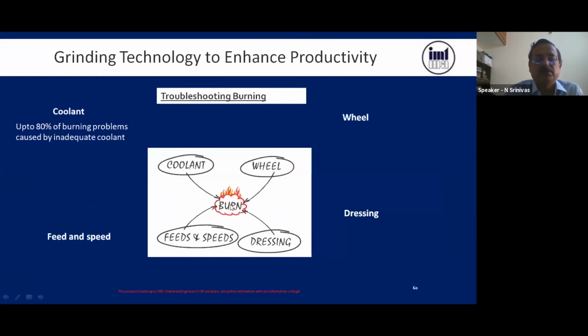For example, burning comes. What are all the causes for burning? With respect to coolant, up to 80% of the burning problem is caused by inadequate coolant. Coolant is very important. So at the right point, at the grinding zone, sufficient coolant should be available, and the velocity of that, and like this, coolant temperature and coolant concentration. Usually the 1:20 or 1:40 ratio. This also matters.